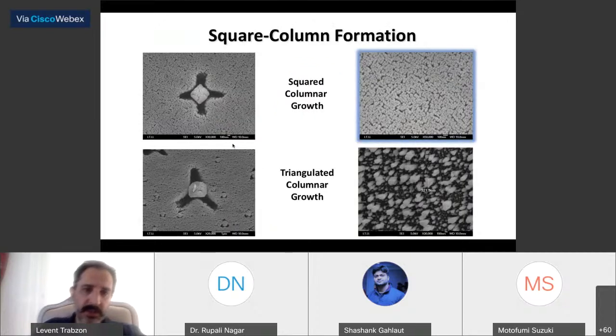For example, on the right-hand side, these are some dirts actually. But since you have the very much enhanced shadowing effect, and by changing the RPM at certain locations with the enhanced shadowing, you can get square-like, much bigger columns. Or if you modify that in a triangular mode, you can get a triangular shape of the shadowing.